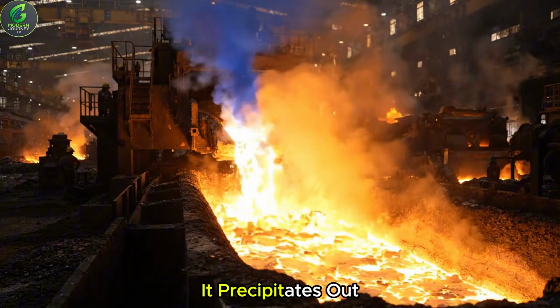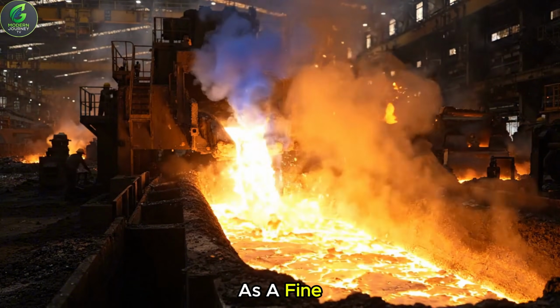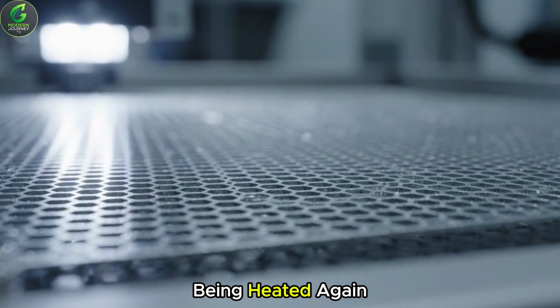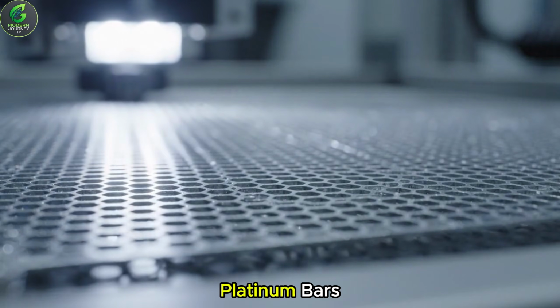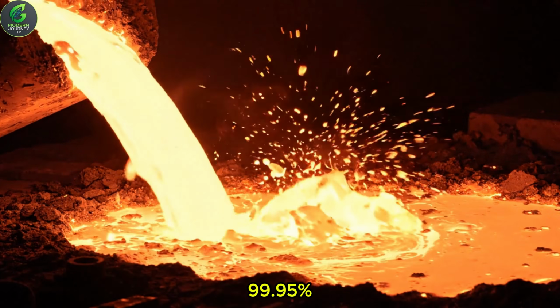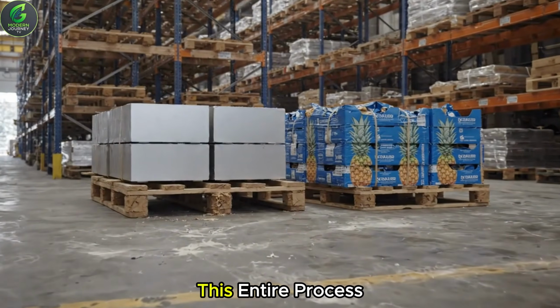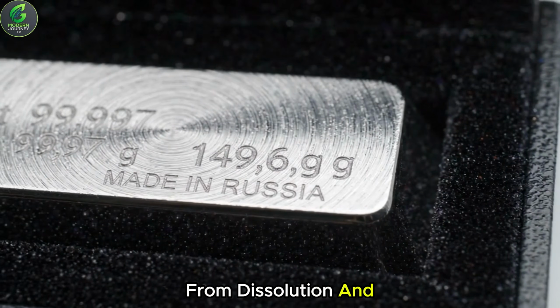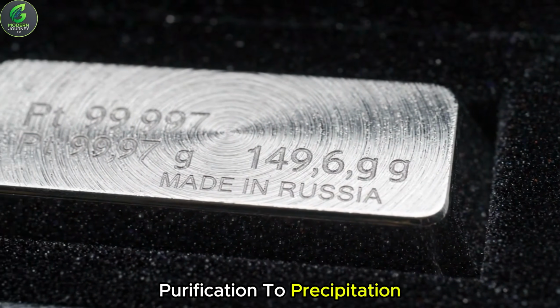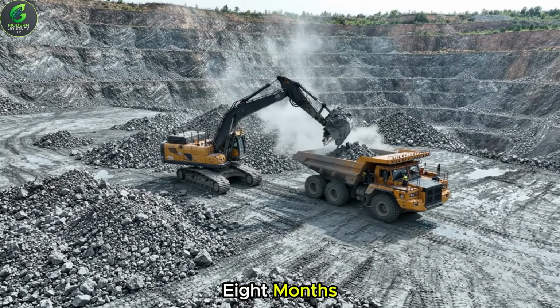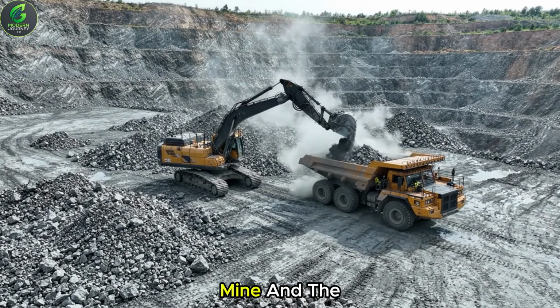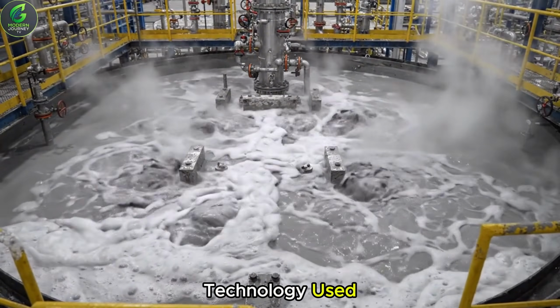At this point, it precipitates out of the solution as a fine, pure powder, before being heated again to form gleaming platinum bars with a purity of up to 99.95%. This entire process, from dissolution and purification to precipitation, can take anywhere from 6 to 8 months or even longer depending on the mine and the technology used.